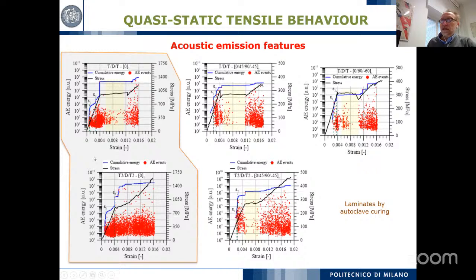And then you see that the main difference between the sublaminates is the acoustic recording during the plateau. In this plateau, the main damage is in the first branch, where you have cracks in the matrix, then you start to have fragmentation, and then this looks to be the time where we have progressive delamination.